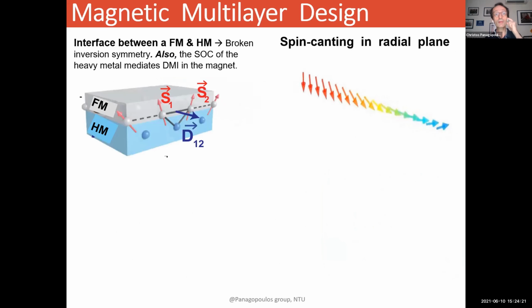Now, therefore, what this says is that the interface between a ferromagnet and a heavy metal would give rise to a broken inversion symmetry, and the spin-orbit coupling of the heavy metal would mediate this Dzyaloshinskii-Moriya interaction in the magnet, which will allow you to have spin canting in the radial plane at this interface.